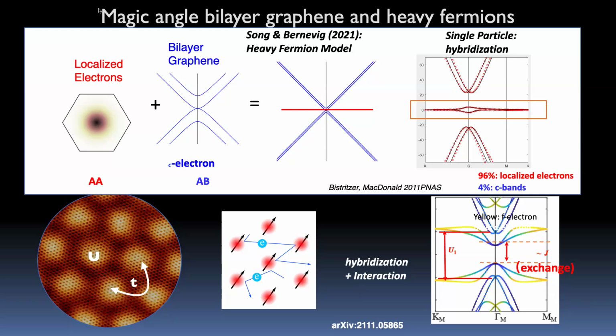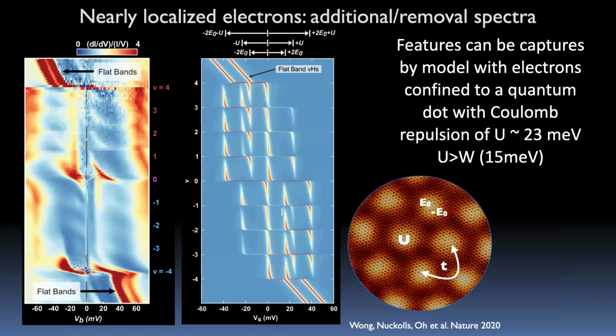I have. Yeah. You're right. From the experiments, with this kind of toy model, you can get some numbers like 25 millivolts for U to match the features of this data roughly. But you can also plug in your wave function and estimate how big U is, and there's a big difference. And this number is actually not that inconsistent with the experiment if you think about two electrons living roughly a moiré distance apart, not using wave functions, putting the gate not so far away, and screening the interactions. This number actually is close to that.